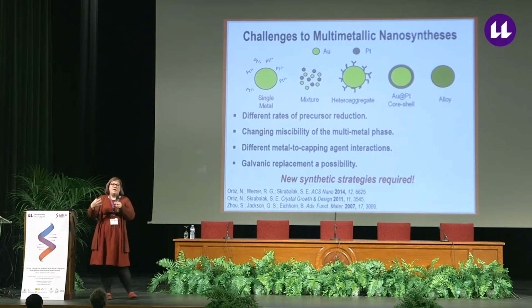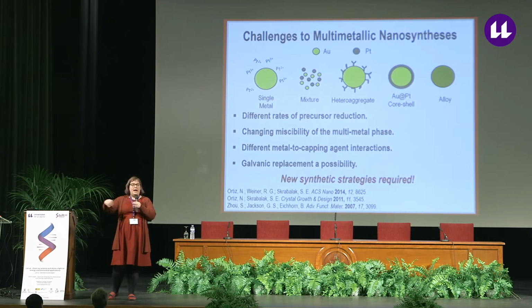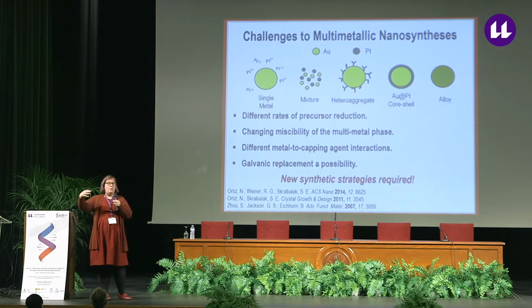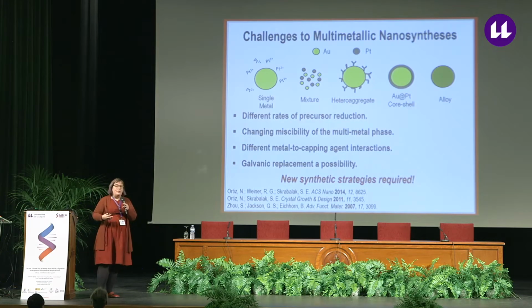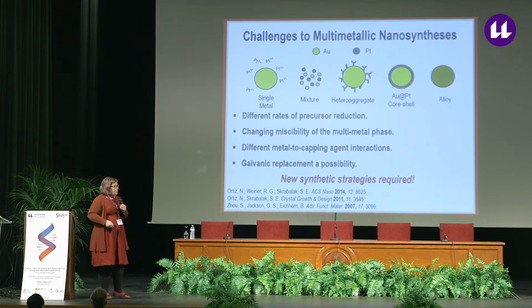But also, even if you are successful in nucleating the desired bimetallic or multimetallic phase, how those metals mix at the nanoscale can change as a function of particle size because of the change in surface energy. And so this makes it incredibly challenging to make a predictable outcome from a synthesis, and also how the different capping ligands in a colloidal synthesis interact with the surface of a nanoparticle. They're going to change throughout as the composition of your particle changes. And so new synthetic methods are broadly needed,